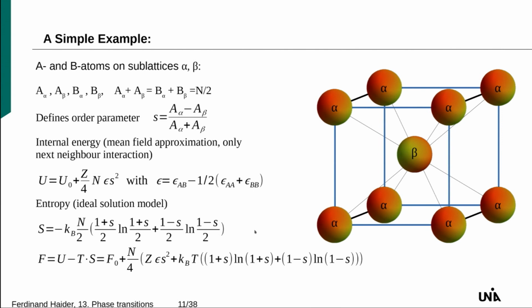If you go through it, perhaps it reminds you of something I already showed. You have this x times ln x terms here. In this case it's 1 plus s, the order parameter. Here I call this order parameter now s, not psi, but it's the same as what I called psi before. So the number of possibilities you obtain like this, these two terms, multiplied with minus kB and the number of atoms. So the total free energy of this system in this simple approximation is this here.